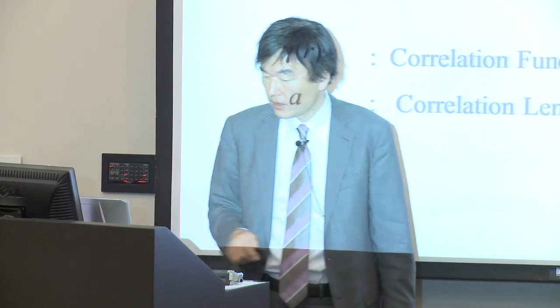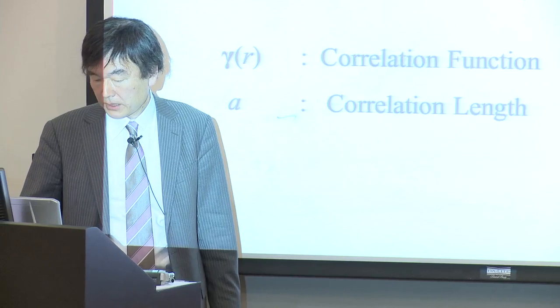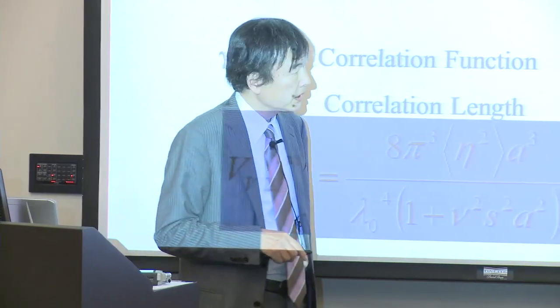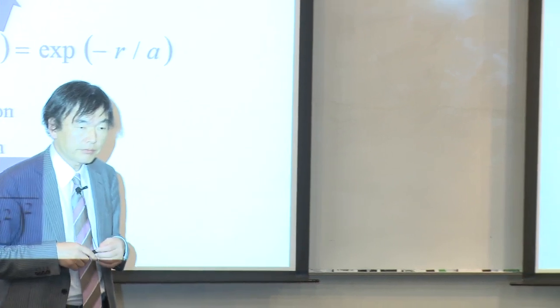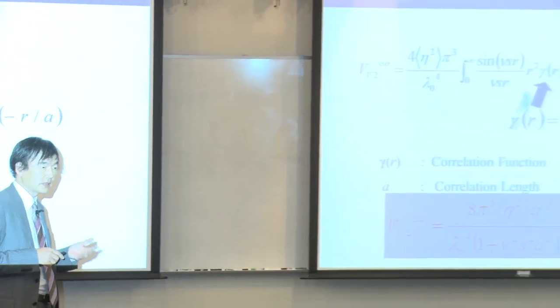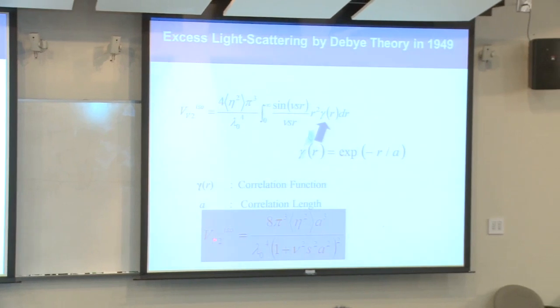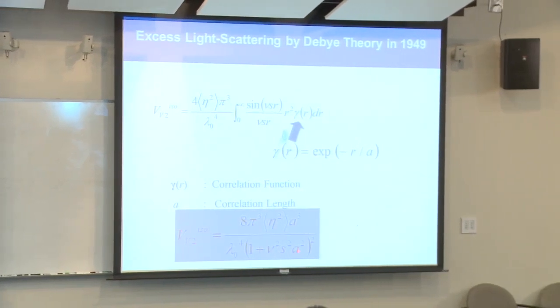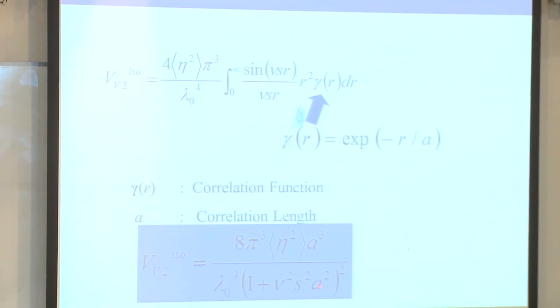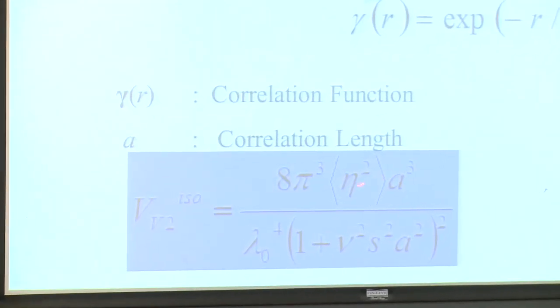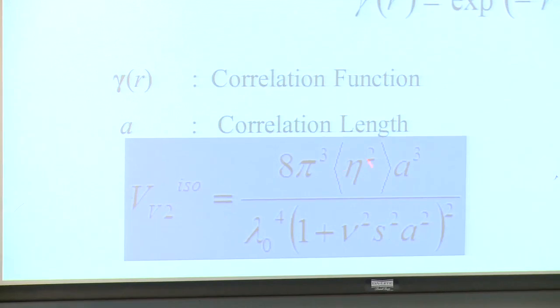And this is a correlation function. This correlation function is inserted into this, and this integration can be analytically solved. This is the solution. This equation became for me a powerful tool to analyze the reason of scattering. Now, scattering loss is a function of the correlation length, roughly the size of the heterogeneities, and is a function of the refractive index differences.